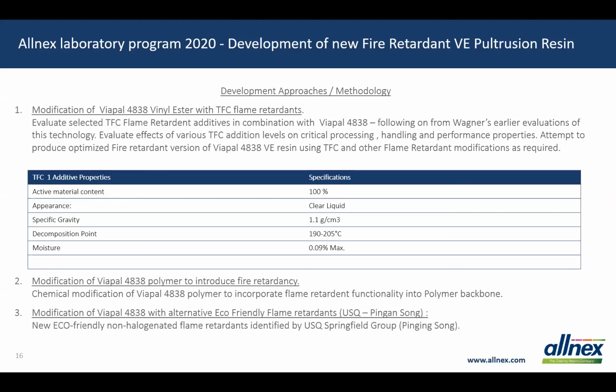We were looking at modification of the Viapal 4838 polymer to introduce some fire retardancy, and this basically would involve chemical modification of the polymer to introduce functional groups that will provide fire retardant properties. So these functionalities are built into the polymer, not post-added. A combination of this approach with the additive approach could be where we end up. It depends on the fire properties that we ultimately achieve in the first phase with blends.